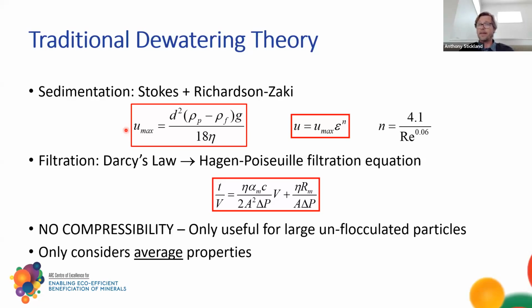And if I want to look then at the effect of concentration, as I go to higher and higher concentration, there are two effects. One is that the particles are now taking up volume, and so there's a net upward flow of liquid that creates a one-minus-phi voidage effect. But there's also an effect of interrupting the streamlines around all the different particles, and so as I get more and more particles, we tend to have a slower and slower settling rate. There's an empirical rule called the Richardson-Zaki equation that says the settling rate at any concentration will be the settling rate of a single particle multiplied by the voidage, which is getting lower and lower as I go higher in solids concentration, to the power of some value n, which they give as this.